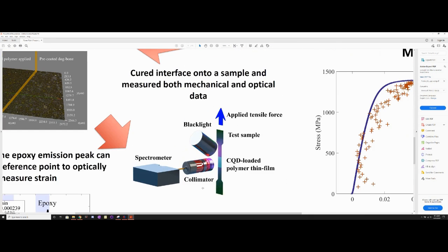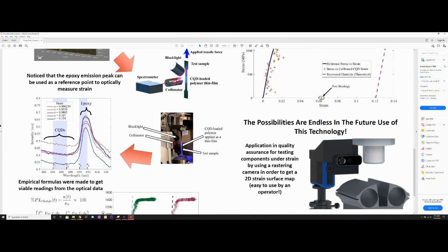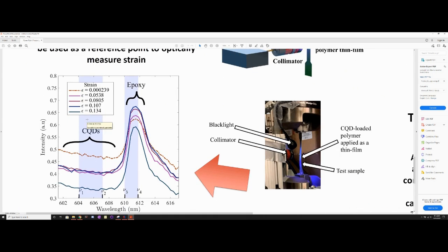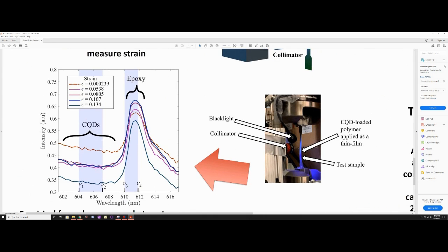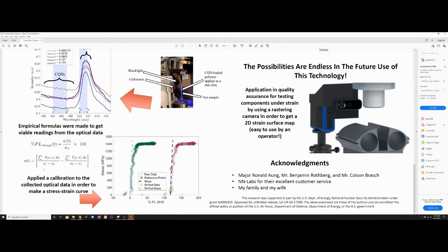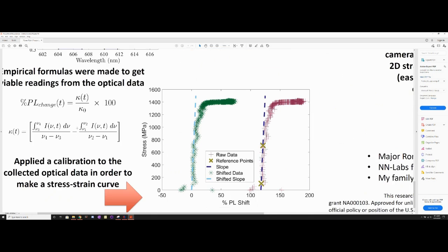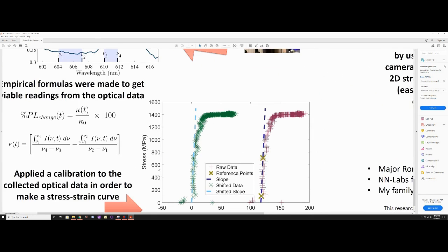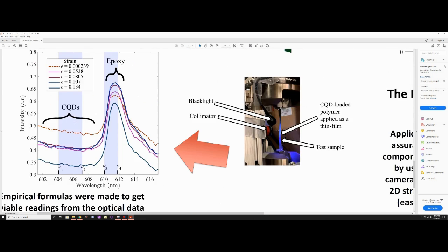This is our experimental setup. It's really simple. We just use a black light to excite the colloidal quantum dot thin film here, and then the emission from the colloidal quantum dots will go to a collimator while the sample is going under tensile strain, and then this is collected by the spectrometer. And then looking at the wavelengths from the spectrometer, you can see over strain that the emission spectra changes over time.